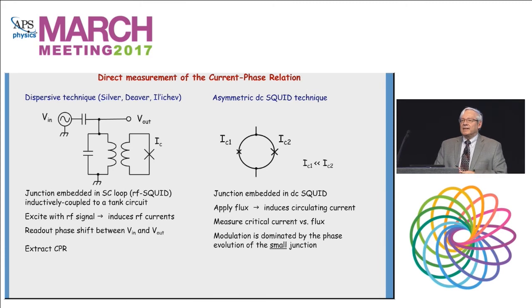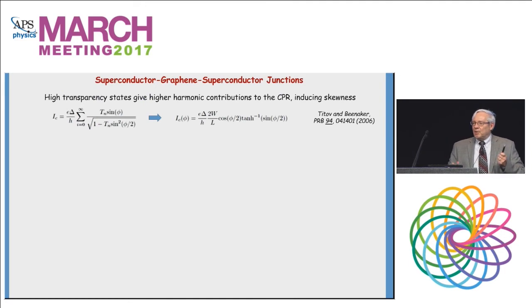And a very nice technique that I'm not even sure who originated, but it's being used a lot now, is to make an asymmetric SQUID. If you have a small junction and a large junction, then it turns out the modulation, if you measure the diffraction pattern, is almost totally dominated by the phase evolution of the small junction. So you can read the current phase relation out almost directly. All these techniques have in common that they're Josephson interference experiments. You have to somehow embed the junction in a multiply connected ring so you can track out the current phase relation. So I was going to run through a couple of quick examples.